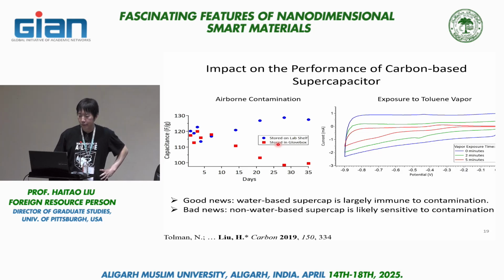Okay. In particular, we expose the active carbon material to air for different amounts of time, and we find there's actually no impact on the double layer capacitance when those materials are exposed to air in a lab setting. Okay, so that's good news.